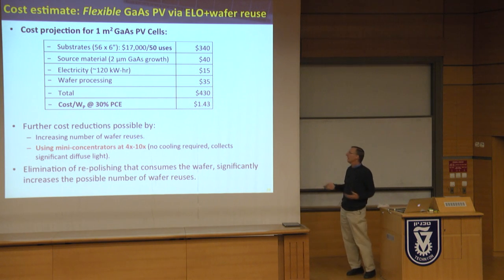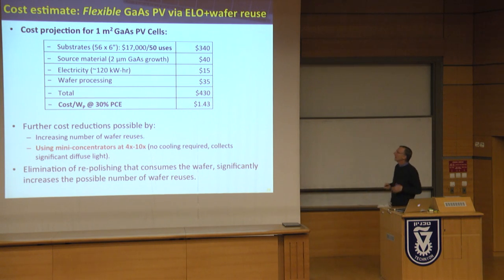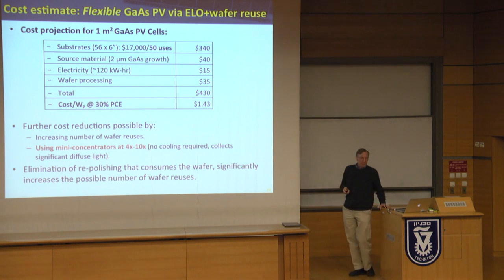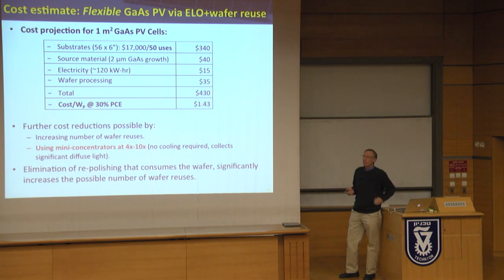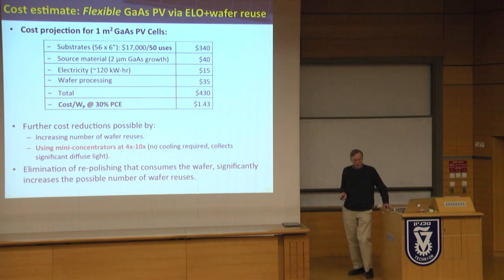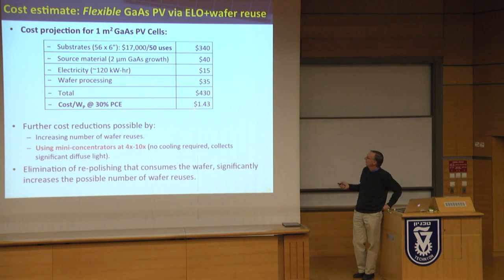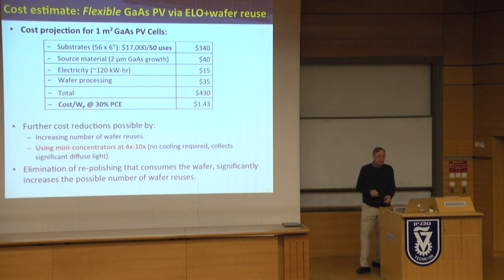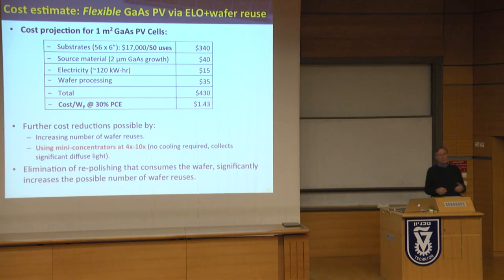And I'm not going to talk about handling, you know, dropping or anything like that. You have to come up with mechanisms to really watch your wafers because you really want them to be part of the capital equipment. The source material is this, electricity, about 120 kilowatt hours to grow this stuff. Wafer processing, the total is $430 per square meter. If we have a 30% power conversion efficiency, if we make a multiple junction cell, let's say, but no concentration, we're about $1.40 per watt, which is still nearly double silicon.